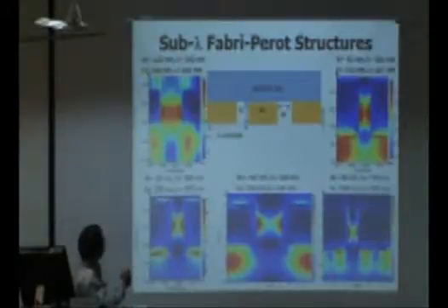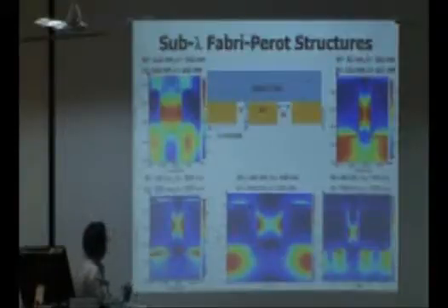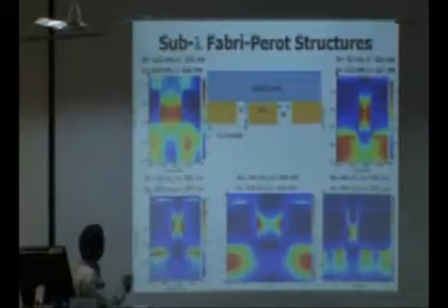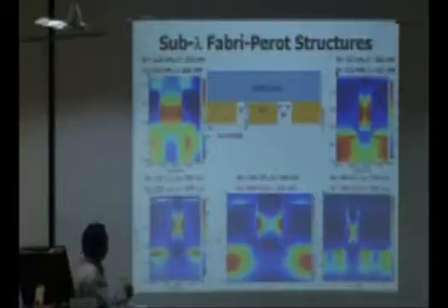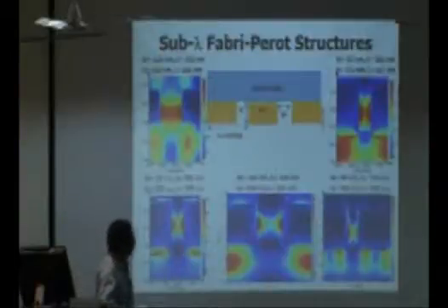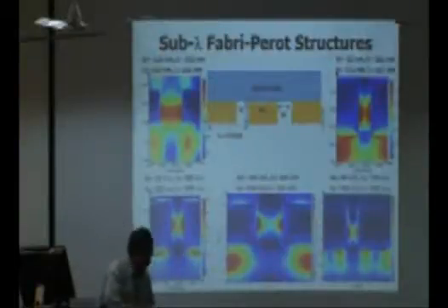So here, for example, the resonance is at 532 nanometers, but the separation between these two gold rods is about 50 nanometers. Okay. So this could have applications, for example, in trapping different nanoparticles and biological molecules.